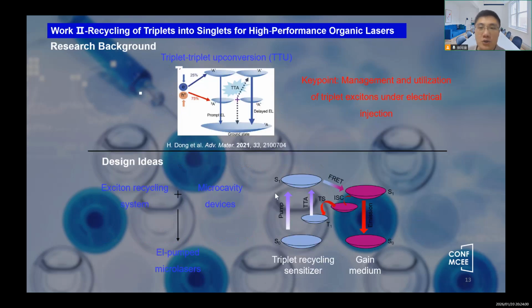Next, I will introduce my second project, recycling of triplets into singlets for high-performance organic lasers. The triplet upconversion process refers to the collision between two triplet excitons under electrical injection. When the triplet exciton density is sufficiently high, it produces a singlet exciton with twice the energy, which then radiates light. This has been proved to improve the external quantum efficiency of electroluminescent devices,